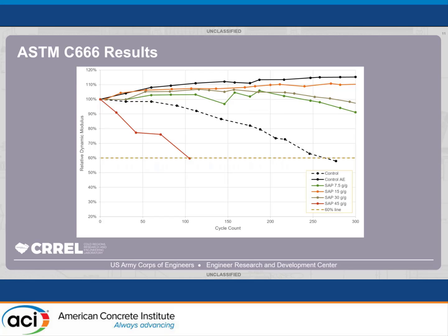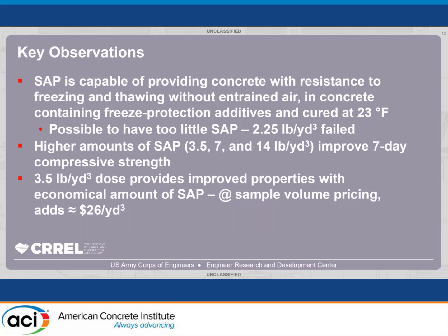Moving into our key observations, we saw that SAP is capable of providing concrete with resistance to freezing and thawing without having to use air entrainment. It also works in combination with these freeze protection additives when you're curing it at 23 degrees Fahrenheit. What we saw from the strength results and from the freezing and thawing results was that it is possible to have not enough SAP. There are just not enough voids, and 2.25 was the lowest amount that we tried.